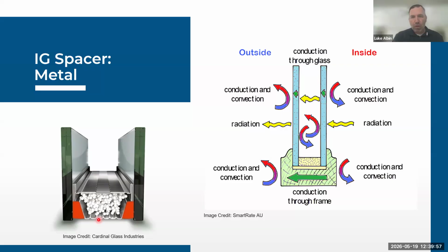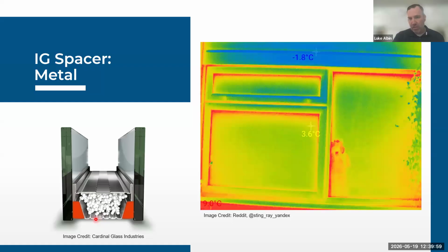So looking back, here's the picture of that thermal image that we had at the beginning of the presentation. You'll notice these dark red and orange areas are around the IGU. That's where this metal spacer lives. And that's why we're looking at better technologies other than metal when we're looking at edge of glass performance. Again, this is also a significant contributor to condensation resistance because we're talking about temperature versus relative humidity.